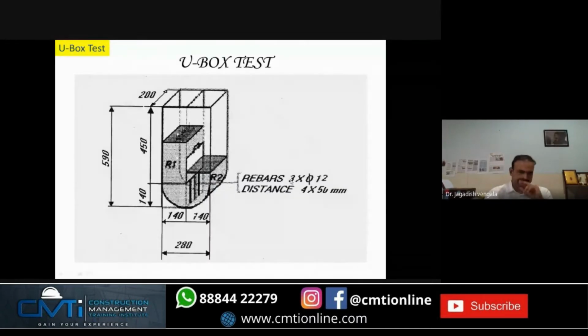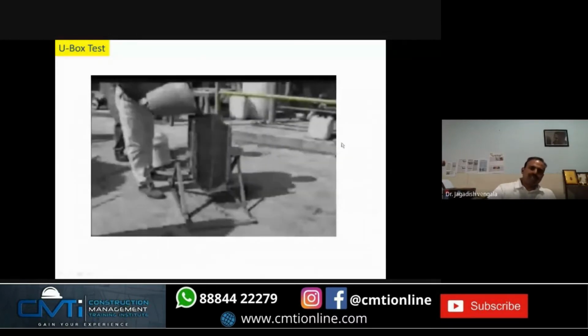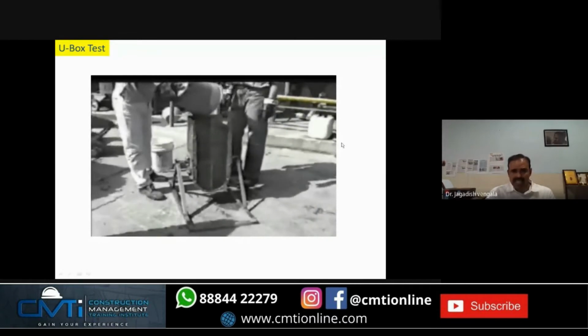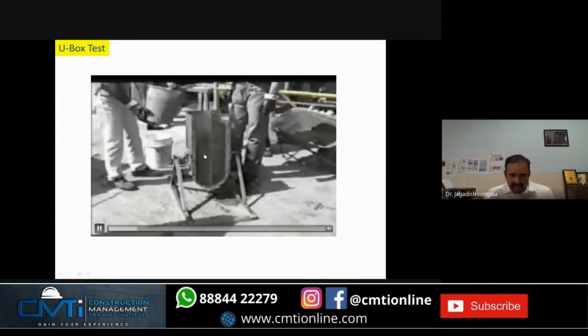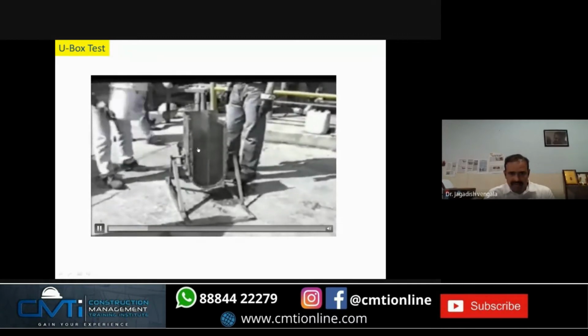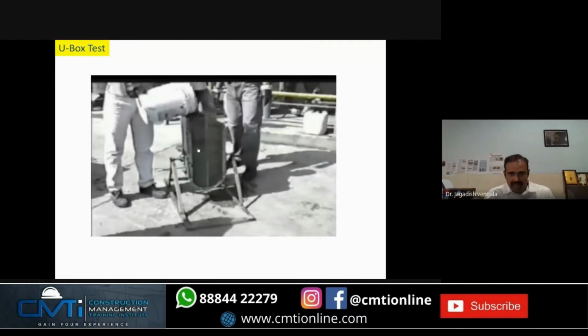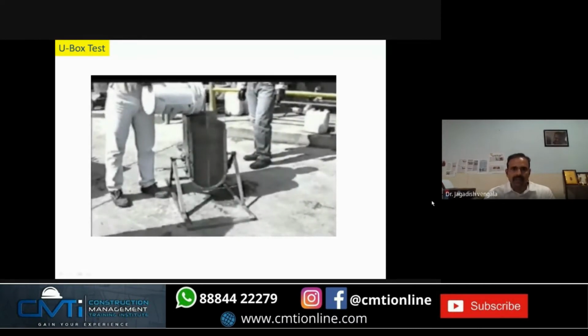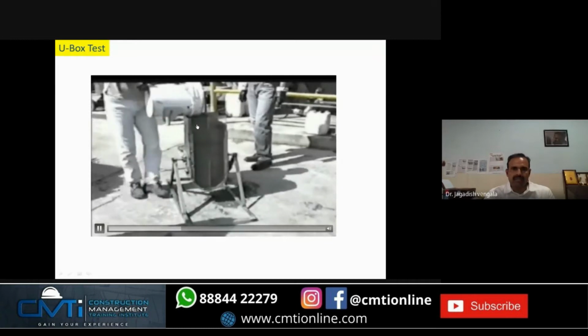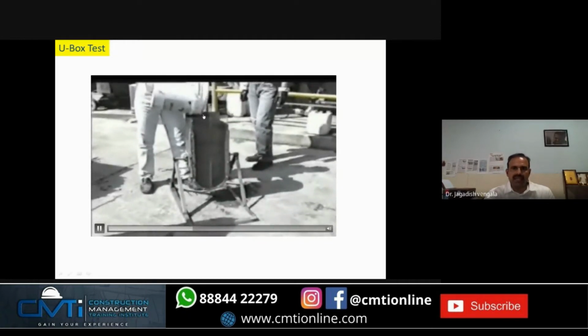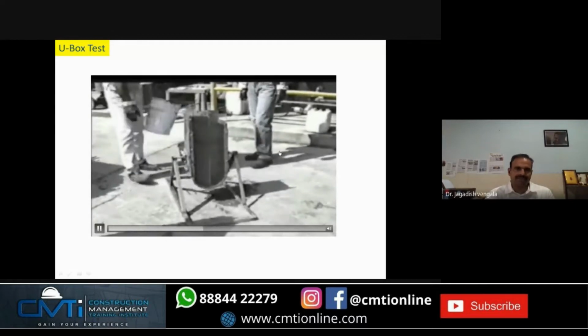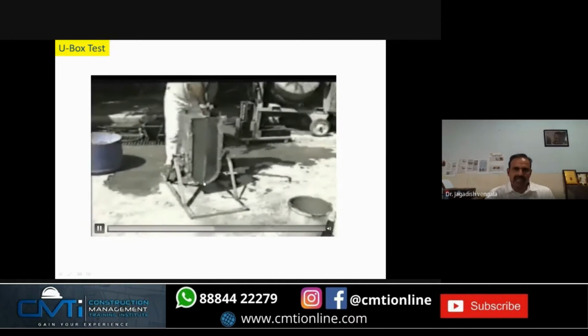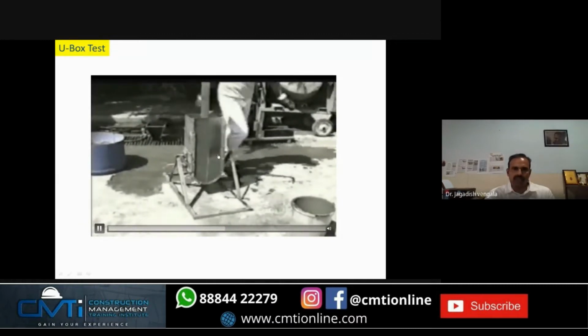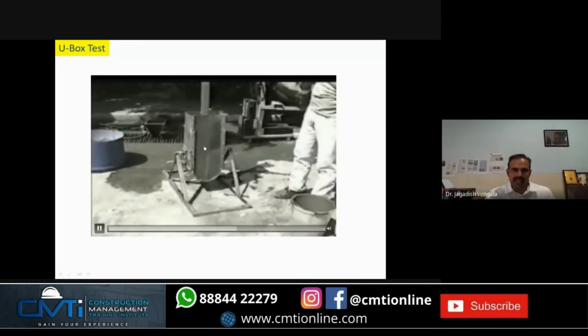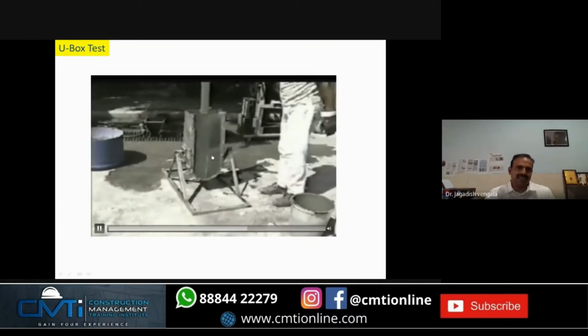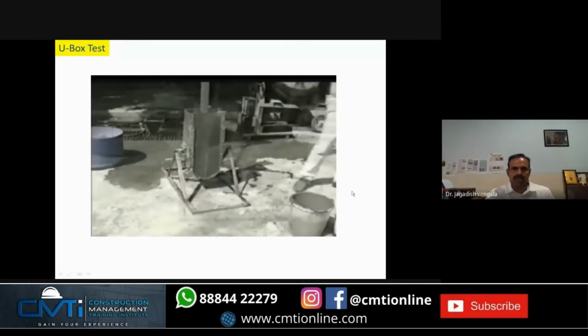These are the U-box dimensions. You can see one of the chambers is filling. You can see the concrete is rising. Concrete has come up to this. By cursor, you can see, and then it slowly comes up to this. Once it is completely poured in one side of the box, you will lift the middle gate, and then it comes to the other limb. So you will measure the height difference, this side and this side. This should be less than 3 centimeters or 30 mm. That is what you do.